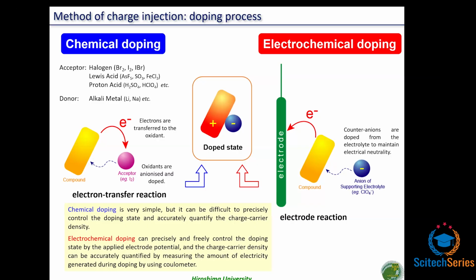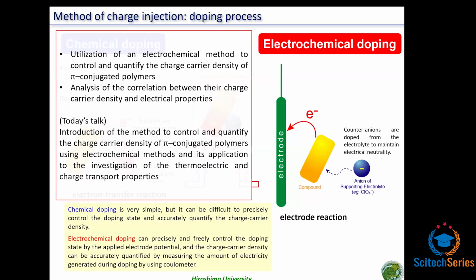With this method, the doping state can be precisely and freely controlled by the applied electrode potential, and the charge carrier density can be accurately quantified by measuring the amount of electricity generated during doping by using a coulometer. Therefore, we utilize an electrochemical method to control and quantify the charge carrier density of π-conjugated polymers and analyze the correlation between their charge carrier density and electrical properties. So, in today's presentation, at first, I will introduce the method to control and quantify the charge carrier density of π-conjugated polymers using electrochemical method and its application to the investigation of the charge transport and some electric properties.